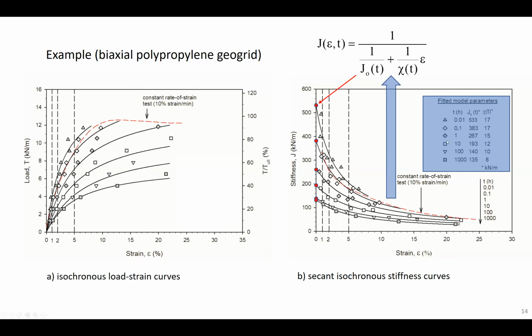Also, you can see again that I have put on both of these plots the 10% constant rate of strain test result. You can see how that test result falls above almost all of these curves on the left-hand side, and you can see also that the computed stiffness curve is also well above the isochronous times at healthy periods of time, in this case more than 10 hours. So again, the take-home lesson here is that just blindly using a constant rate of displacement or strain test will overestimate the stiffness of the reinforcement, sometimes by very large amounts.